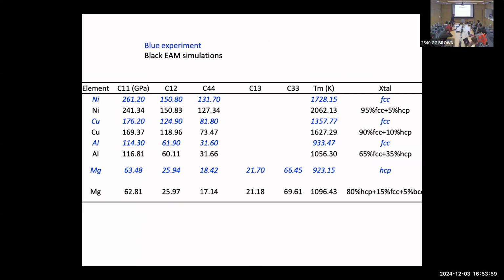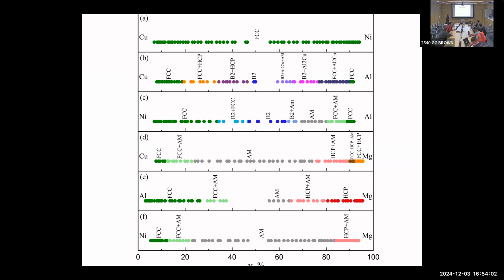On the last slide, the AM means amorphous, right? Yeah. So when something says HCP plus amorphous, it could be both? Yeah, so in general, they're mixing models. We have an X-ray structure factor. We don't have images of the material. The image that we have is the X-ray scattering function. So what you have to do is come up with a model to match the X-ray scattering. So you can say, I'm going to have a mixture model. A fraction of the system is HCP, another fraction is amorphous. And then you can solve for the correct proportions. So wherever it has a plus, that means it's a mixture model, and I solved for the proportion that matched that X-ray scattering. But they usually make sense because it's HCP over here, it's amorphous over here, and then there's a mixture in between.